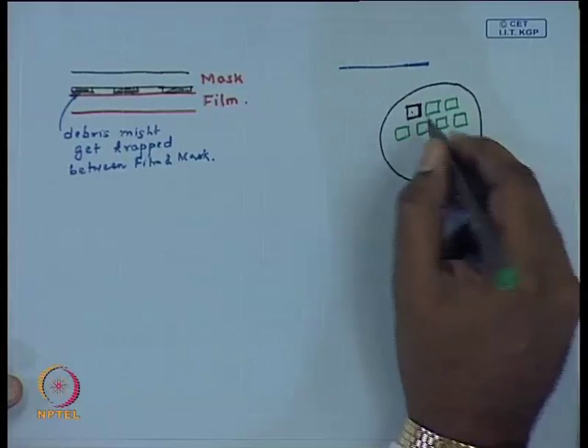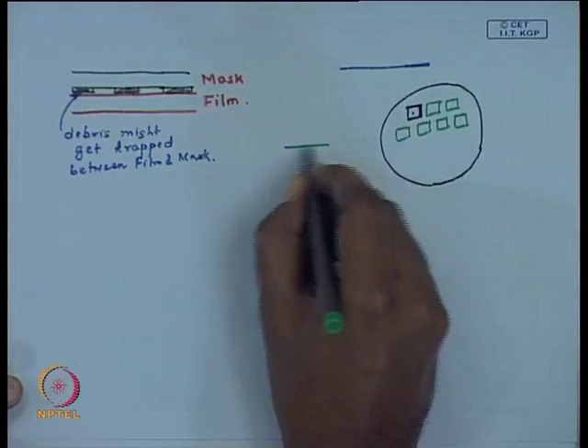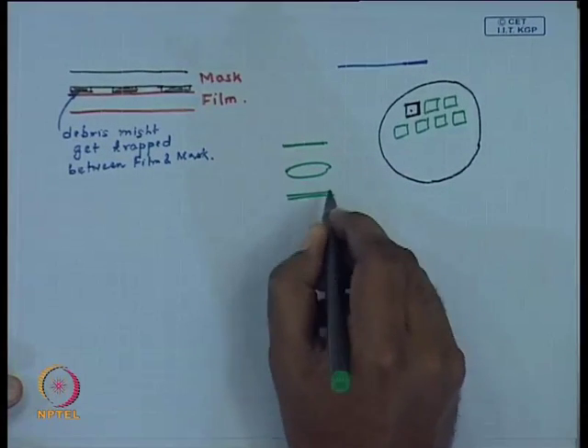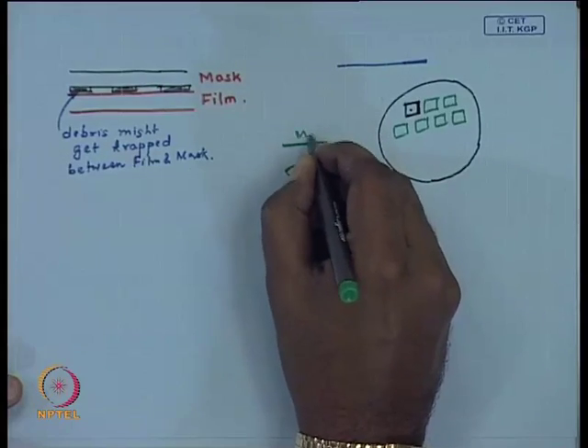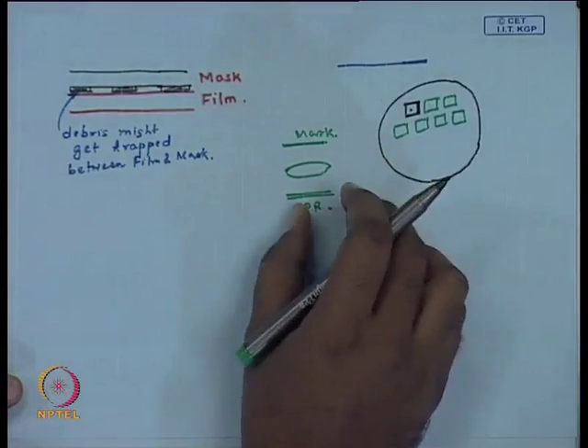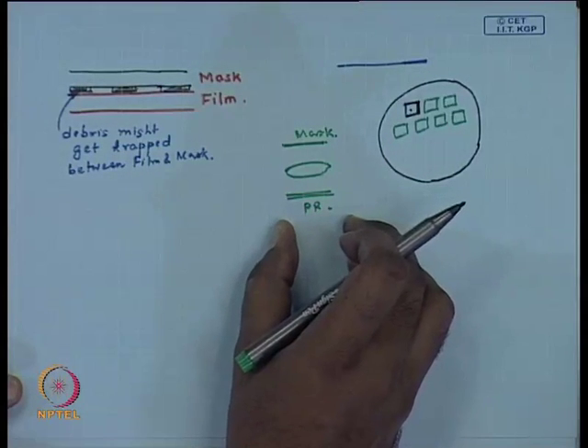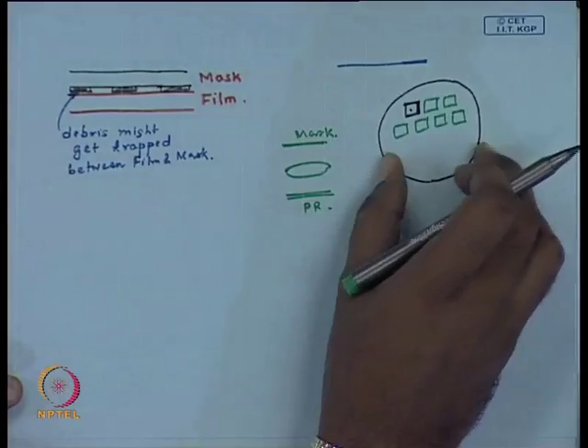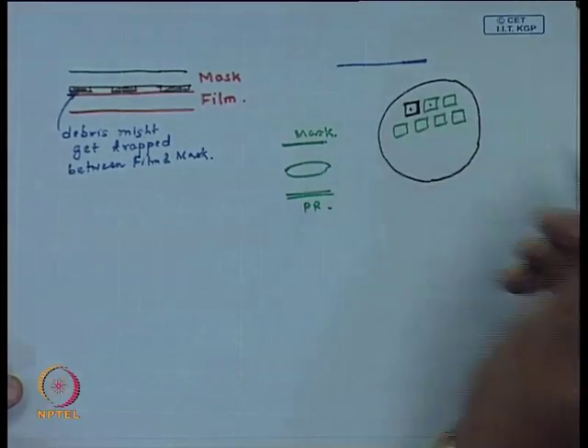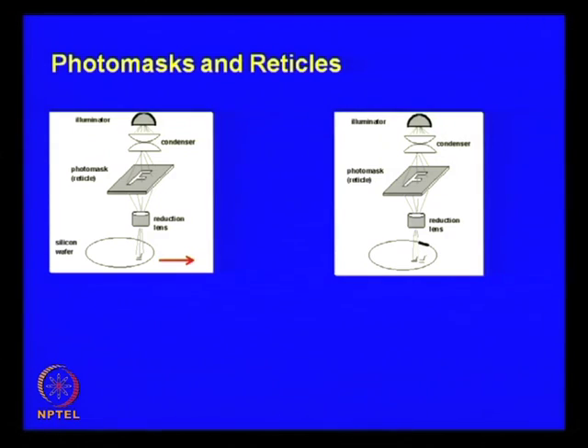So, the easiest thing to do would be, once the exposure is done at this place, here is the mask, here is the lens, here is your photoresist coated wafer. Once it is done, maybe you just raster it, or with the help of a mechanized motor, you just shift your wafer from this location to this location and then repeat the experiment. This is exactly what it means. So, you see here you have a wafer, this is the photomask, and you do the exposure, you get the pattern once, and then if you want to reproduce the pattern, you just move the wafer in this particular direction.